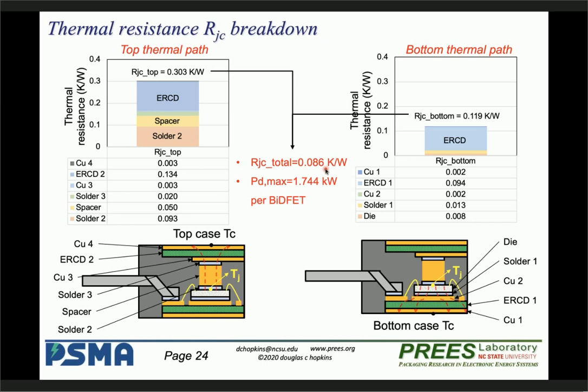0.086 degrees per watt. And besides the RJC total, we can further calculate the maximum power that the power module can dissipate. So it is around 1.7 kilowatt per BiDFET. And you can notice that this value is extremely high because I assume a perfect cooling condition at both top and bottom cases. Which means this value is the upper bound or upper limit of the heat dissipation capability. So you cannot exceed this value.